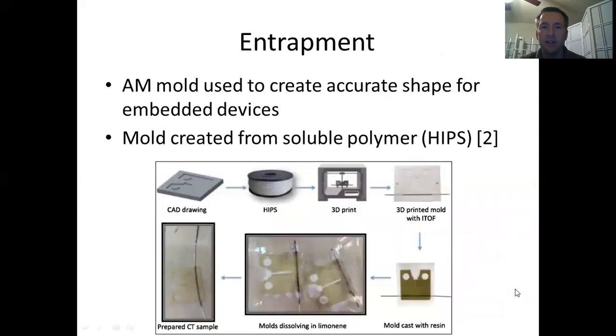So entrapment is the idea of having parts embedded into your composite, and you need to account for the shape of the part, and you also have to be able to get the mold out. So one way to do that is by using a soluble polymer such as HIPS. So this picture is a great example of the process where you design your part in CAD, you use your HIPS, you print it out, and then you embed your sensor or whatever it is. Then you cast your composite, and then you dissolve the HIPS, and then you end up with your final sample.